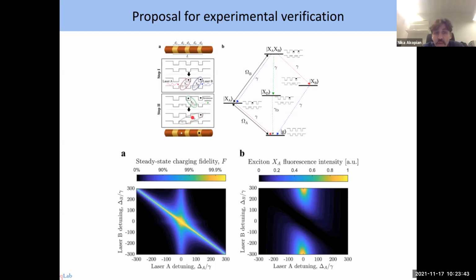So we need a way to know if we successfully created such a pair. The way to verify it experimentally is to monitor this transition all the time, because if we created this electron, we cannot excite it anymore. And this is what's shown here. Again we scan laser A, and 0 is 0 detuning, so it's resonant with the level here. And again we scan laser B, the same as here. But now we monitor the fluorescence from here. If we have successfully created this state, then we can no longer excite an electron-hole pair here, and the fluorescence will be 0. So this is the experimental measurement of detuning from laser A and detuning from laser B, measuring exciton A fluorescence intensity. And if we see this, then we have created an electron and a hole in two remote quantum dots, and they are stable.